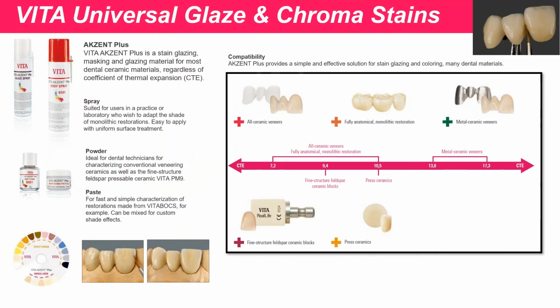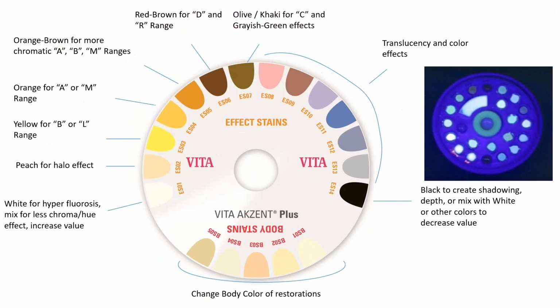If you do stain and glaze it, which most of us do, we use what's called the Accent Plus in our system. This is basically a universal stain glaze, a low temperature glaze. We glaze this material around 800 degrees Celsius. We have all the different colors like everybody else. You can mix them, you can match them, you can effectively create your own characterization stain color. Most of them, except for your black and your very dark pigmented stains, are all fluorescent. Your LT glaze is highly fluorescent to begin with, but you also have additional high fluorescent glazes if you need to use them. But these are the different colors, just like everyone else.